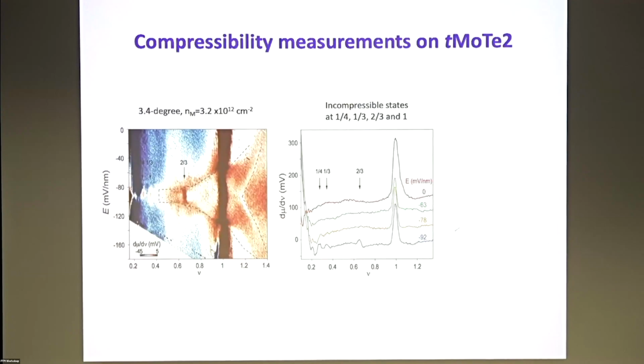So this is a map of the incompressibility, the dμ/dν, as a function of the electric field and filling factor of a particular sample calibrated to be 3.4 degree with a Moiré density of about 3.2 × 10¹² per centimeter squared. Okay, and you can sort of see that it looks like the electrostatic phase diagram that I asked you to remember. In the small electric field region, roughly enclosed by this dashed line here, the bands are topological. Once you go to high enough electric field, the bands are non-topological, as you will see.